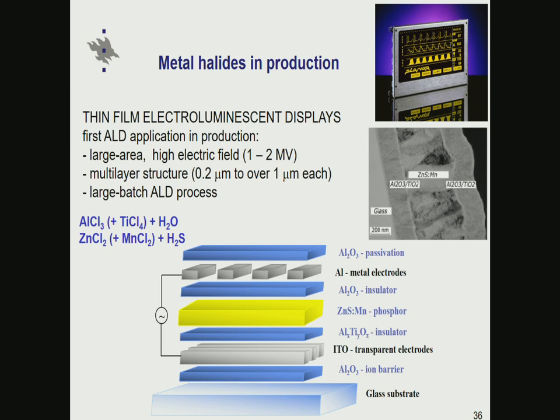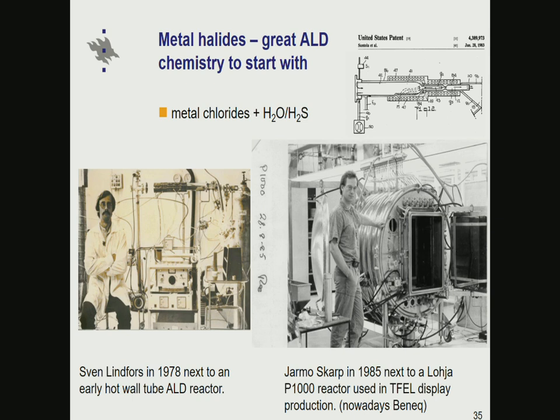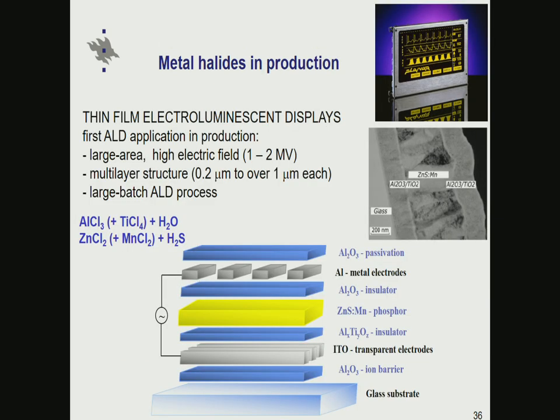In the beginning, all the precursors were metal chlorides. Nowadays they also use some metal organics, but still the chlorides form the main basis of this production scale use. And to exploit ALD in making this thick layer structure, a very important fact was that they went straight ahead to large batch processing, which means that inside this kind of a reactor one can load tens of these displays, as shown in the next slide.